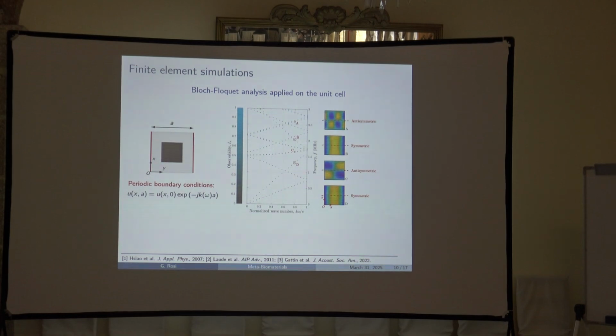And so basically we can discriminate between modes because the specimen will be inserted in water, so the only incoming wave will be a longitudinal polarized incoming wave from the left with a normal incidence. So basically this wave can only see the symmetric modes. So if you play with some average of the field, you can end up with an observability coefficient that makes you see that our longitudinal wave can only see this dotted point solution, and so actually you have an elastic bandgap for longitudinal waves.